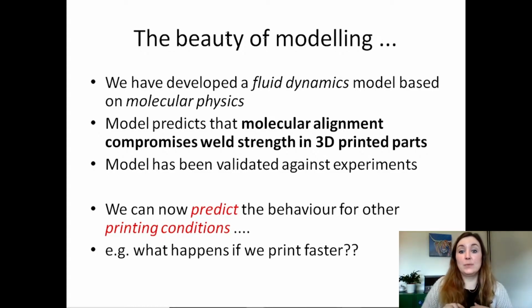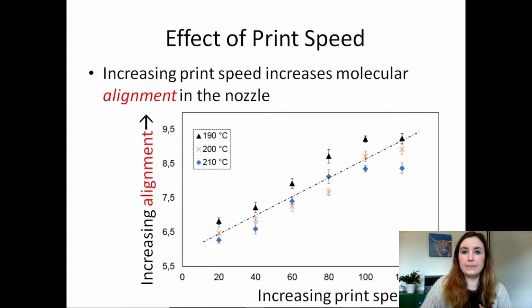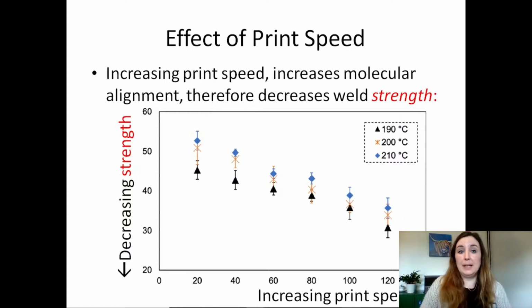So one question we can ask is what happens if we print faster? If we print faster, we have to force our molten plastic through the nozzle at a faster rate. That increased force is going to stretch out our polymer molecules even further. So we're going to get an increase in the molecular alignment with increasing print speed. So what does that mean for our weld strength? If we have increased molecular alignment and increased print speed, this is going to decrease the strength of our welds. So printing faster is really detrimental to building up the strength between these printed layers.